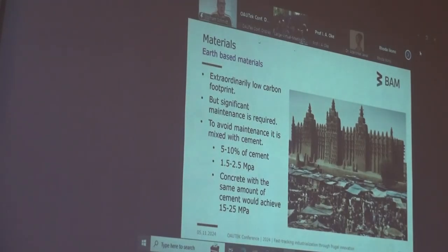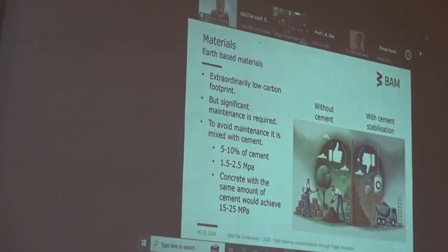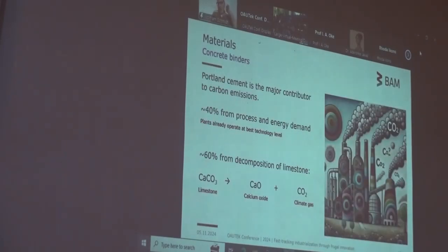If we would use the same amount of cement and put it into real concrete, we would achieve something like 15 to 25 megapascals. So we have to very carefully also discuss the topic of using soil-based materials, because without cement, they are very, very green. But if we use cement-stabilized soil-based materials, that can become a burden, because we have to reduce the cement consumption worldwide. And that's the next topic, which is concrete. And a major contribution to the carbon footprint of concrete is actually the cement. It makes about 85 to 90% of the carbon emissions.